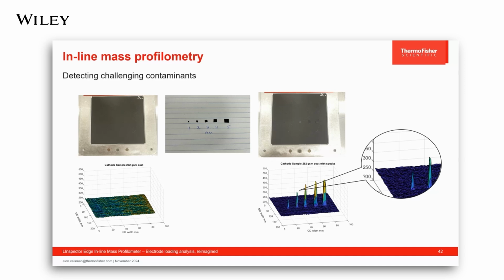A sample of NMC cathode was measured, and the mapping of it is shown in the bottom left corner. We then took a few flakes of the same cathode material and placed them manually on top of the sample. You can see these flakes in the middle. They range in size from approximately 1 to 5 millimeters. We then measured the sample with the flakes on it.